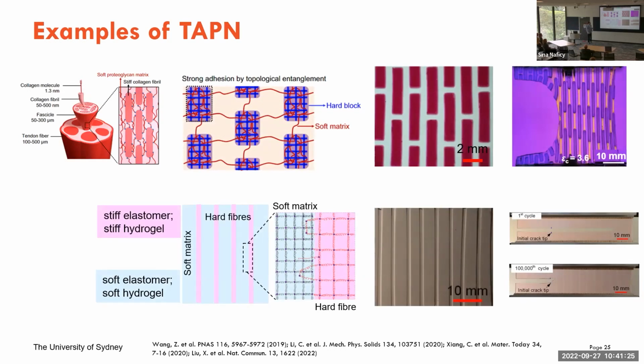The top one is a hydrogel-based material, a very thin film. The bottom one is an elastomer-based material. They don't need to be hydrogel or elastomer. You could use the same concept for either of these, it doesn't matter, as long as there are soft networks. As you can see, we have a soft matrix, which can be formed very easily. Within that, we have a stiffer network. At the top, we have blocks oriented in one direction. At the bottom, we have fibers elongated.